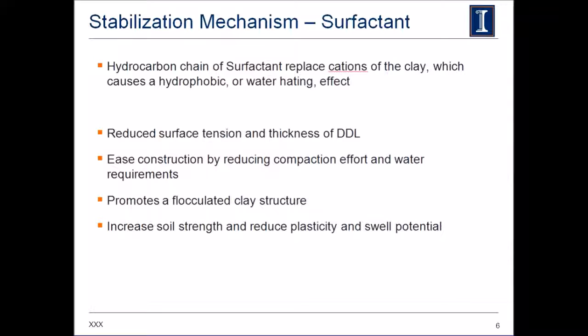Another effect of this is that it lowers the optimum moisture content. Although this effect has no direct impact on strength gain, it eases construction by reducing compaction effort and water requirement, or it increases the density and strength at certain moisture content.